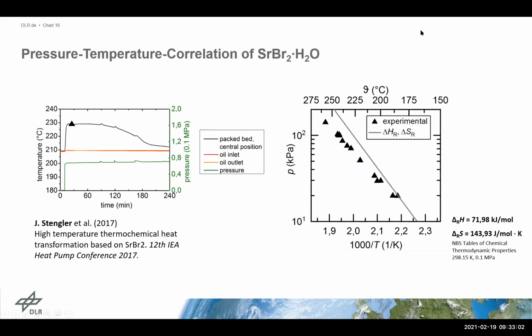My colleague Jana Stengler was doing a lot of investigation here, did her PhD on this topic. Here you see a first work, beginning of her PhD, where she was analyzing the exact equilibrium of this strontium bromide water material. You see here on the right a comparison between the theoretical line and our experimentally determined equilibrium line. And what you also see is that in the relevant pressure range, we have temperatures between, let's say, 160, 170, and up to 270, 280 degrees Celsius. As I said, you could adjust this by changing your solid.